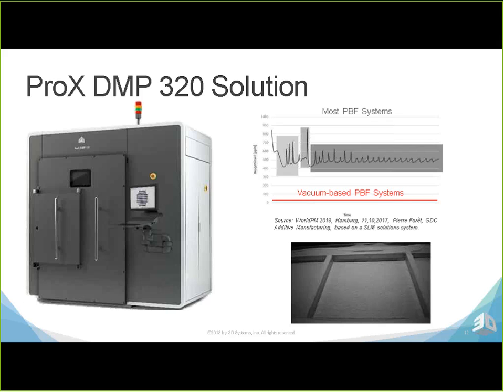So for highly reactive materials, titaniums, aluminums, these metals at elevated temperatures are sponges for oxygen. So if you start with a grade 23, kind of a metal grade titanium, you may have 5 to 6 uses, depending on the surface area of what you're printing, before you've now lost the chemical composition of your grade 23 powder and either have to dope it or you now have to kind of downgrade the powder. Same thing goes with other superalloys like your heavy nickel Inconels. As you're building these components with higher oxygen environments, you're going to end up reducing weldability and reducing fatigue strength.